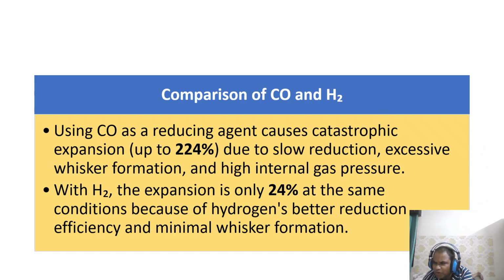So, the carbon monoxide versus hydrogen showdown. As it shows, CO causes a massive 224% expansion with slow reduction and whisker overload. Hydrogen keeps things tight at just 24% expansion thanks to its lightning fast reduction and minimal whiskers. Hydrogen wins the battle hands down.